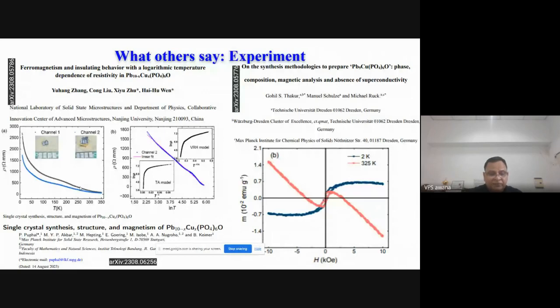This is the Keimer one, dated 14th August. And Claudio Felser from Max Planck Dresden was also there. Many good groups reported that this transition is basically from copper sulfide. And if at all there is something in this system, it is the strange magnetic behavior, some sort of diamagnetism, and that may be the reason behind what is happening in this system.